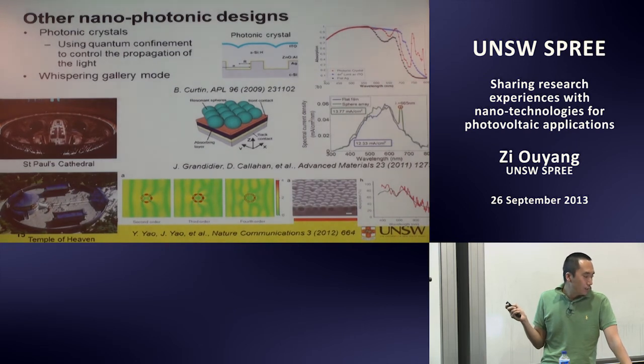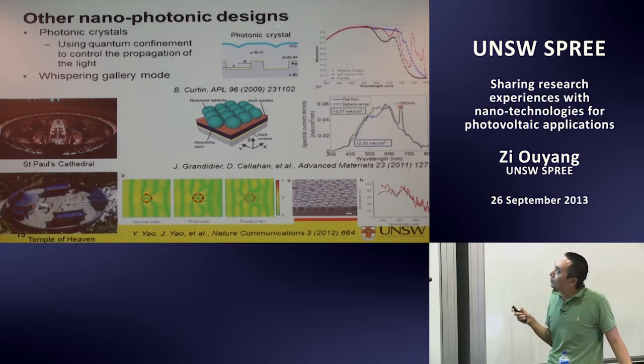So, finishing plasmonics, another thing in nano-photonics design is photonic crystals, where you use quantum confinement to control the propagation of light. It's like you introduce a band gap for your semiconductor material, for your electron band gap. This is an optical band gap. That means at some point the light is not allowed to move in one direction, one angle. If you have a look at this, you actually find a very large boost at some point of the spectrum, actually higher than the 4n squared predicted. But at the sacrifice of other wavelengths.